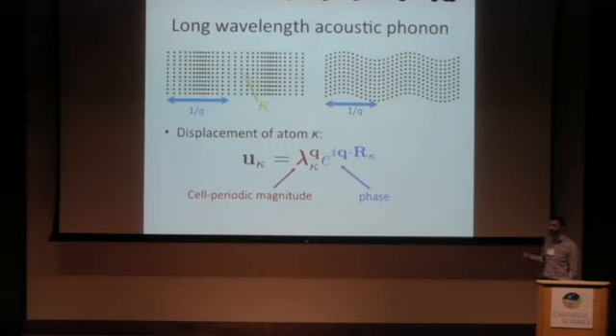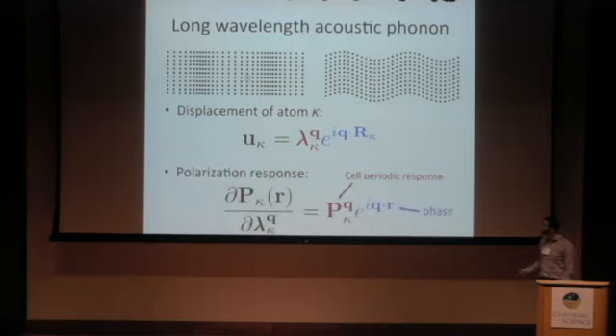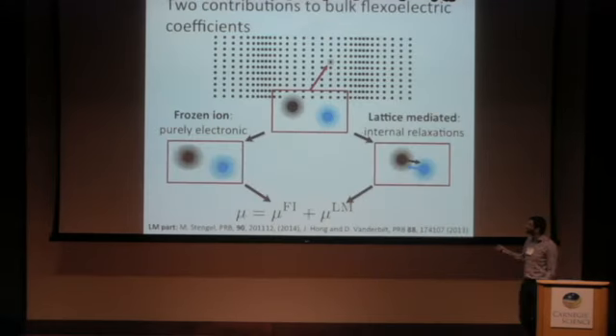Using some well-developed methodologies in density functional perturbation theory, we know that we can describe the atomic displacements of sublattice kappa as a result of a phonon with a cell periodic part modulated by a phase with wave vector q. And in the linear regime, we can also describe responses to these atomic displacements, such as the polarization response, also as a cell periodic response modulated by the same wave vector q. And so if we're smart about factoring out these phases, we can just focus on the cell periodic parts of this displacement and response, and therefore only do calculations on a single unit cell. So in these schematics, these dots could correspond to a single atom in a unit cell, or they could correspond to a unit cell themselves, which in a general crystal may have several atoms.